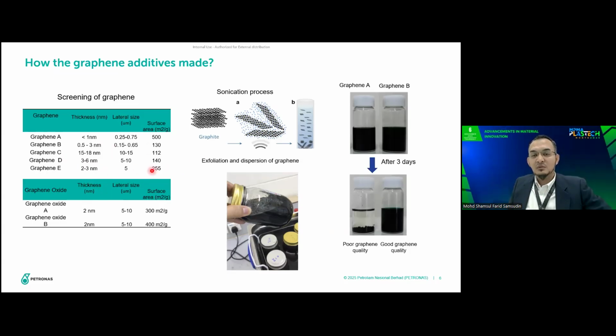From these graphenes, we do a kind of screening. We put the graphene in a certain type of solvent, and then we do sonication using an ultrasonic bath at a certain temperature and hours. After that, we do a screening to monitor the performance of graphene, whether the graphene particles exfoliate easily. Normally, if the graphene is of very good quality, it easily exfoliates and disperses well in the solvent. So this is what we have carried out in our lab.